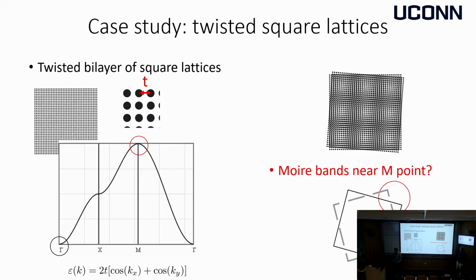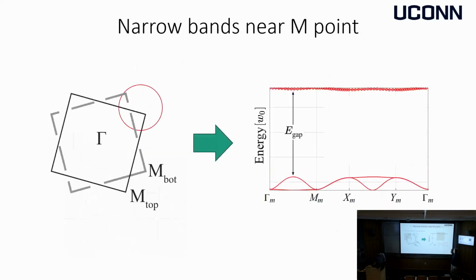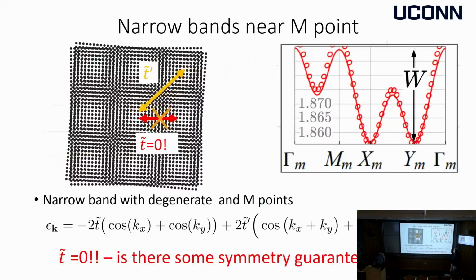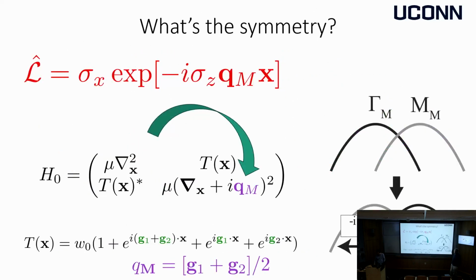So is this effect robust against lattice relaxation? I would believe so, because my understanding is that as long as you keep the symmetries and moire period intact, the only thing that's going to happen at the continuum model level is that you can renormalize these parameters, and maybe make some higher order terms relevant, but they don't break the symmetry. That's the important point.